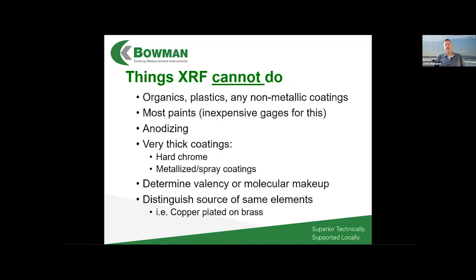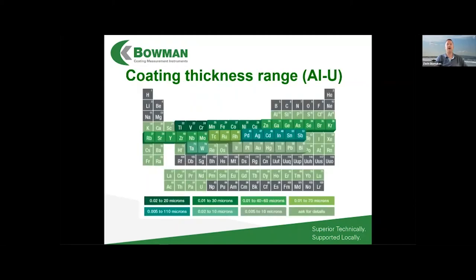And we can't distinguish between layers of the same element. So if you had something like copper plated on brass, which is a copper alloy, we can't really tell where the copper is coming from, because you got a copper-based metal with copper plated on top. So you basically have to fix one or the other. So if we know what the content of the brass substrate is, if we fix that copper composition, measure the brass substrate as is, then measure the copper plated substrate, then we can kind of subtract what that base signal was out of that. But without knowing what that was to start with, we can't distinguish where it's coming from. So again, these are common limitations of any XRF. Just wanted to point that out.